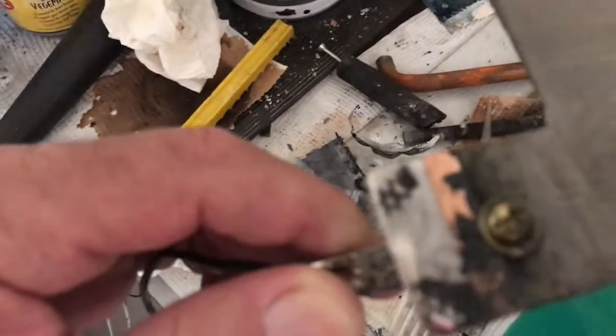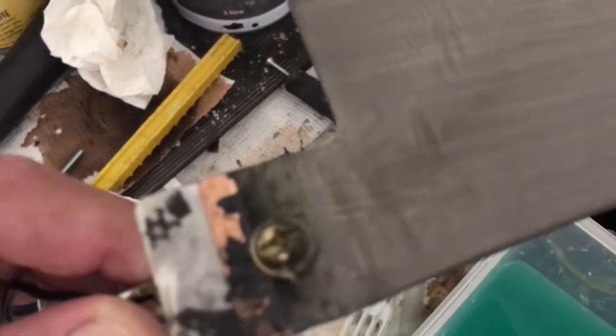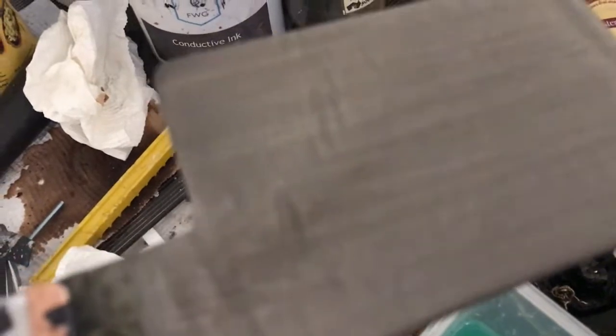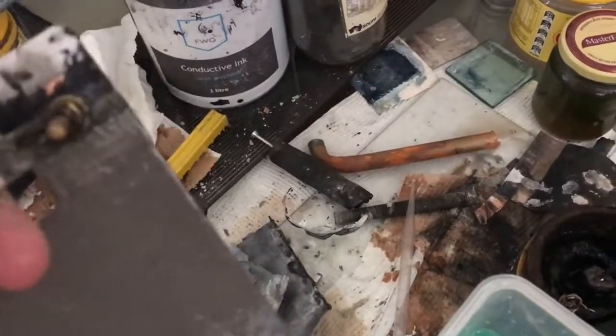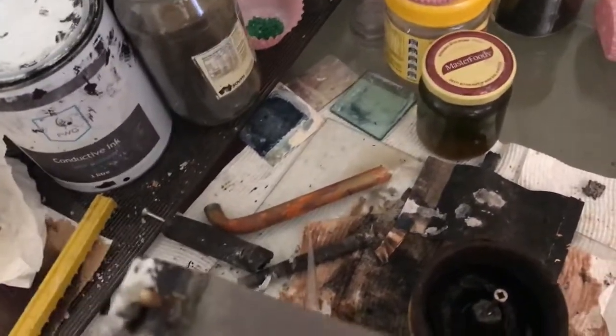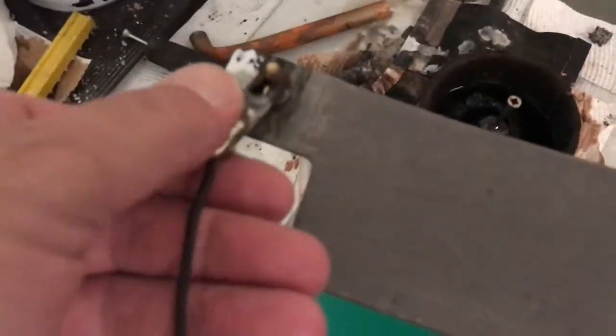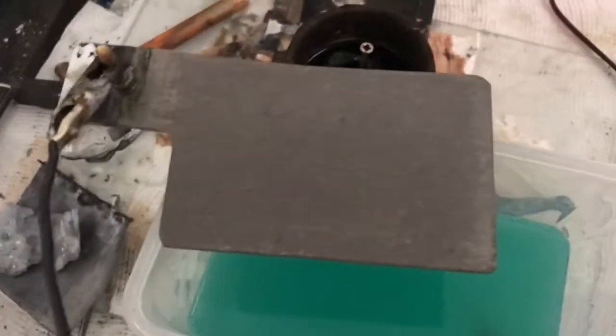FWG conductive ink, just to give it extra gripping power, because this plastic was a serving tray and they're really shiny. It's a real hard plastic. It cuts best with a grinder actually. It doesn't melt, it just powders off, so you've got to wear a mask. So success with the copper plating, and then also nickel plating on top of the copper, which helped greatly.